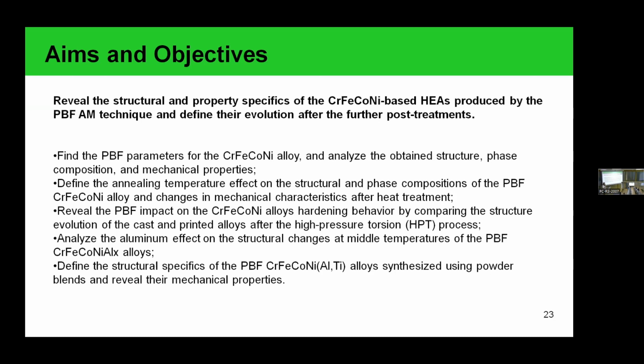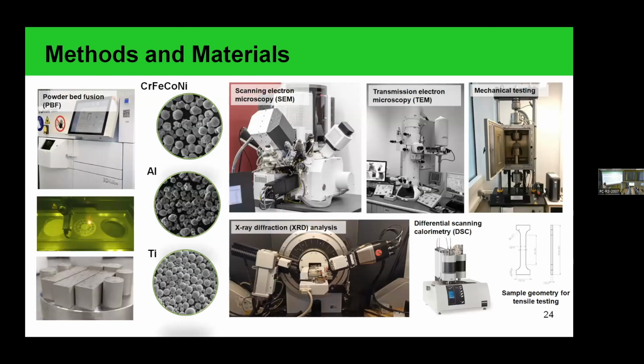On the next stage, we add the aluminum to our system and analyze the structural distribution and also phase distribution in this material. And in the last stage, we observed the properties of the material alloyed with aluminum and titanium. For this purpose, we used powder bed fusion 3D printers, 3 types of materials, the 4-component system, aluminum and titanium, several microscopy techniques, X-ray diffraction analysis, and also a mechanical test machine to analyze the mechanical properties of our materials.